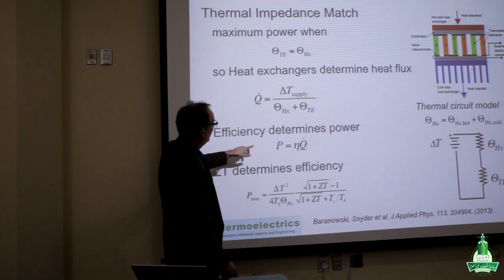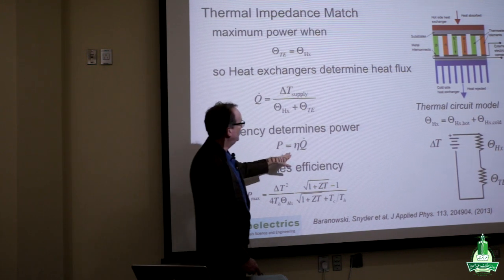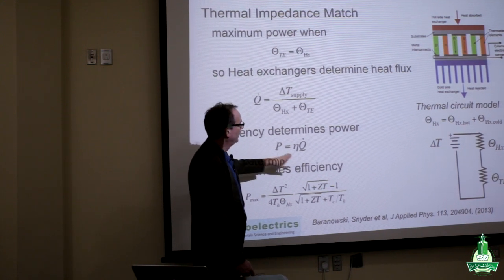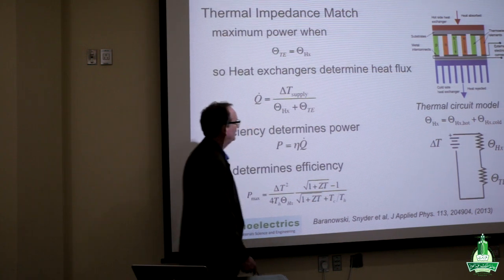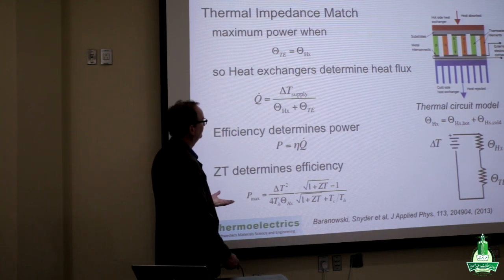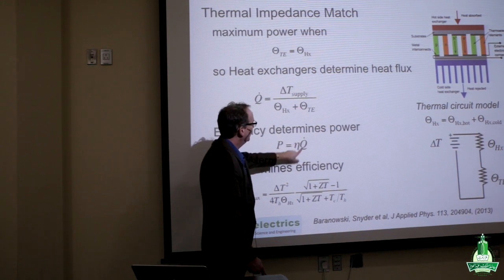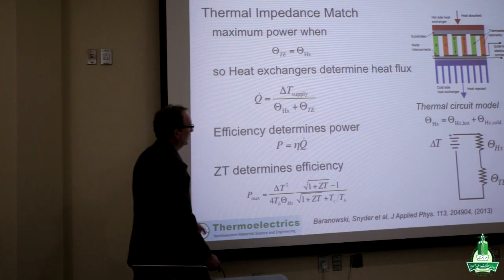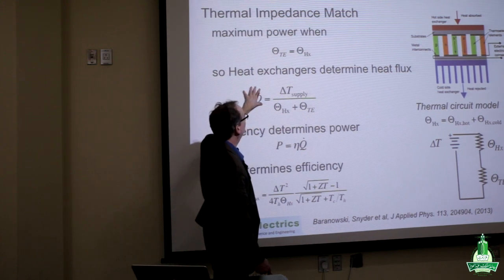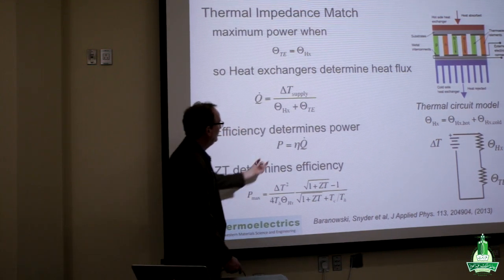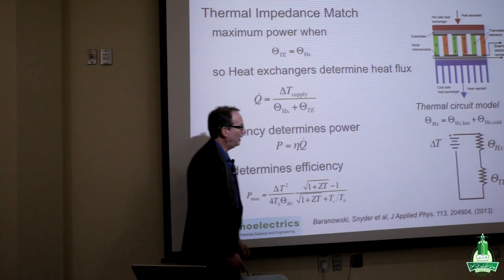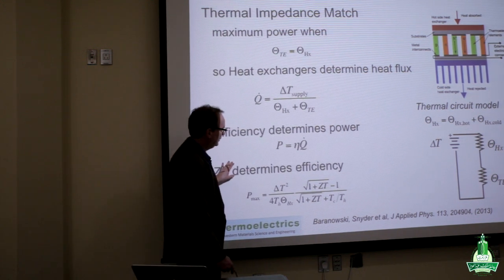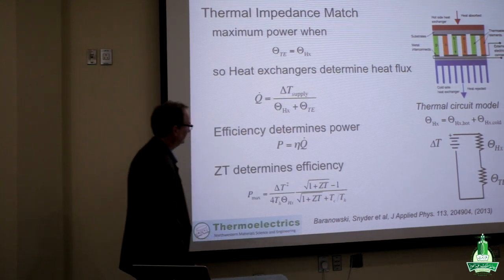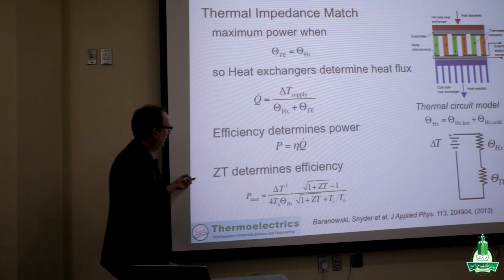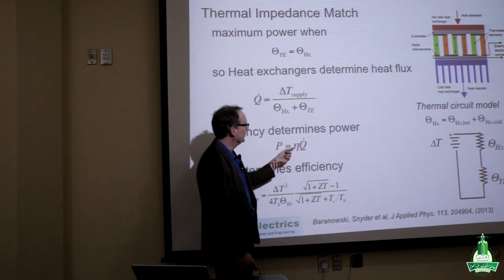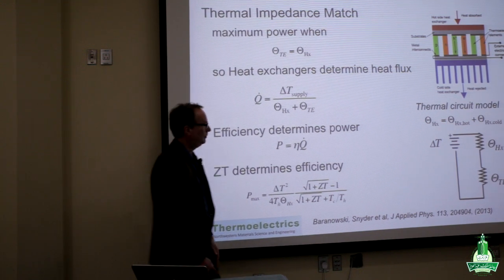Now, our electrical power output of our system is due to the efficiency of that system times the heat flow through the system. And so what that means is that we can separate these two effects. We can maximize the heat flow power, which is due to thermal impedance matching. But then to maximize electrical power, it also means maximizing this efficiency. And we know that efficiency is maximized with our ZT equation. And so the conclusion then is that our ZT parameter, which determines efficiency, is also going to determine our power.